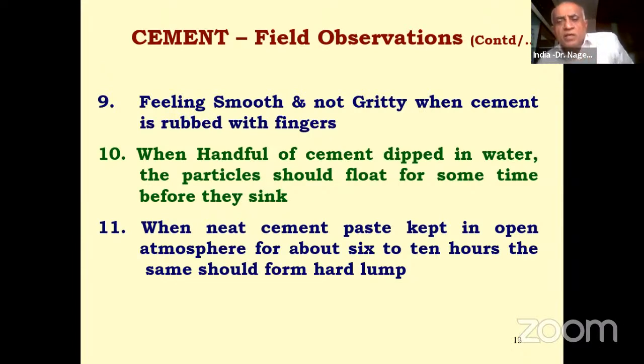This checks whether the cement has sufficient specific gravity or not, because the specific gravity of water is 1, whereas the specific gravity of cement is 3.15. Cement particles are heavier. They will only float for some time and then slowly start sinking to the bottom of the bucket of water. So this is a very important aspect. When neat cement paste is kept in the open atmosphere for about 6 to 10 hours, it should form a hard lump. That indicates there is no setting or hardening issue with the cement.